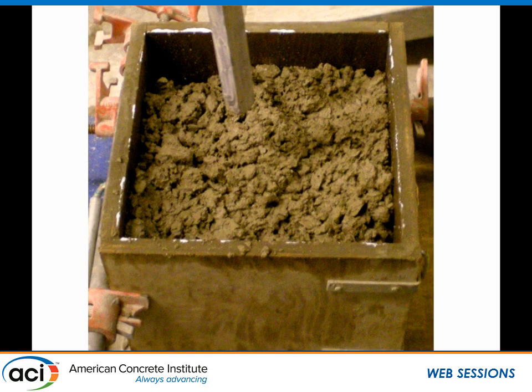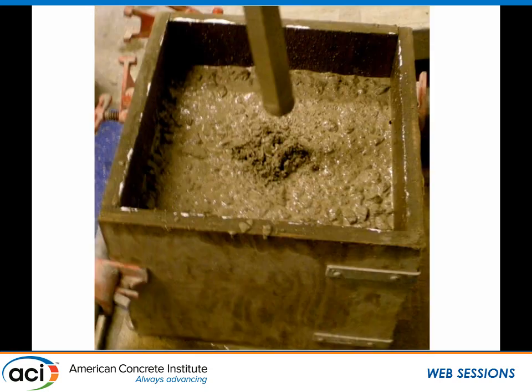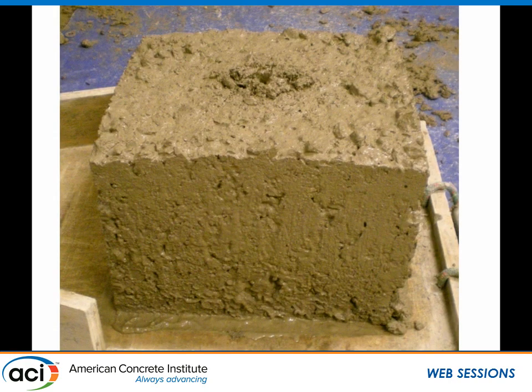Let's look at a mix that did well. The vibrator's going in. Look at that sphere of influence — look how you've changed the surface. When you vibrate the concrete, you remove the voids around the walls. So when you take the edges off, it looks like a perfect concrete brownie.